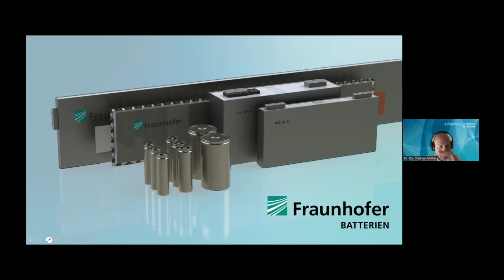These problems you don't have with lithium titanate. This material you can use as nano material with very small diffusion length in the particles. And you have, let's say, safety to the lithium metal deposition of 1.5 volt, which means the energy density of this material is not so high because you lose 1.5 volts of this voltage. So this is more for high power batteries.